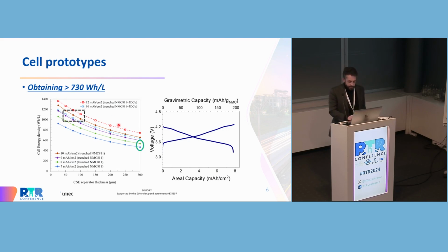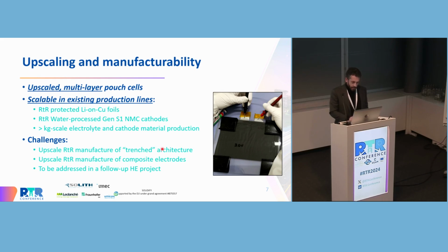So the challenges we are currently facing are mostly related to the increase of the electrode loading, the cathode loading, and at the same time the decrease of the separator thickness, which may cause the failure of the cell. One goal of the project is the upscaling of the pouch cell to a multi-layer pouch cell, and then the upscaling of the existing process in order to match the characteristics of the existing production line. So we basically want to move to a roll-to-roll process where we aim at producing lithium anode and a cathode in a continuous roll-to-roll process at a scale which is higher than a kilogram scale.